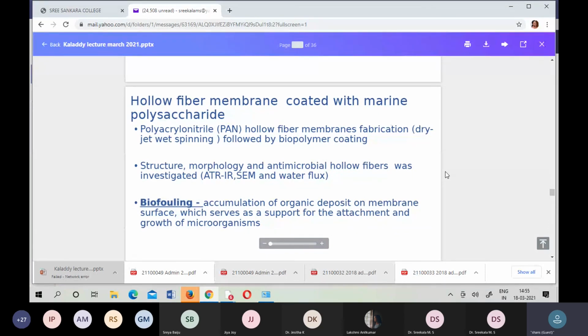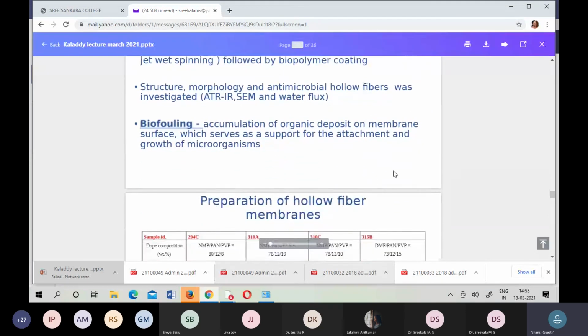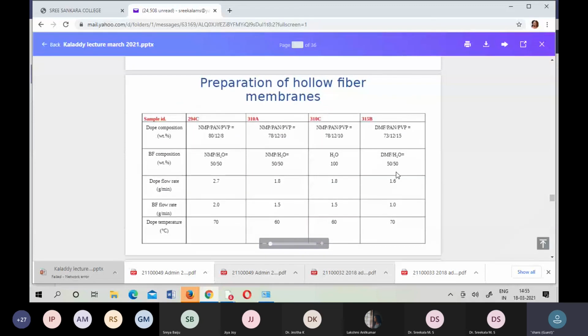What we did is, out of all the polymers, polyacrylonitrile is quite stable compared to polyether sulfone, polysulfone, polyvinyl fluoride, all the commercial polymer membranes. So we took this polymer and tried to make a hollow fiber. For the hollow fiber we used the jet spinning method, and this piece of work I did in Italy. I prepared the hollow fiber, characterized it, and checked it with a coating of our chitosan. Chitosan again comes from marine resources.